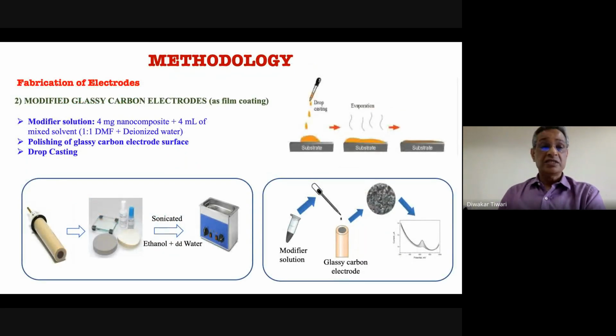Then we extensively characterized these materials. But this time, instead of the carbon paste electrode, we used the glassy carbon electrode. The surface of this glassy carbon electrode has been modified with the help of our materials. So what we did is, we mixed these nanocomposites with DMF and deionized water.